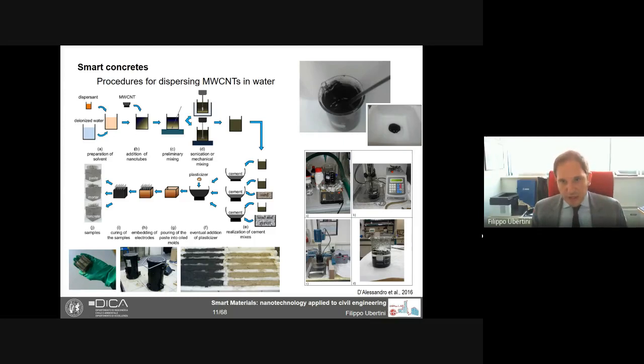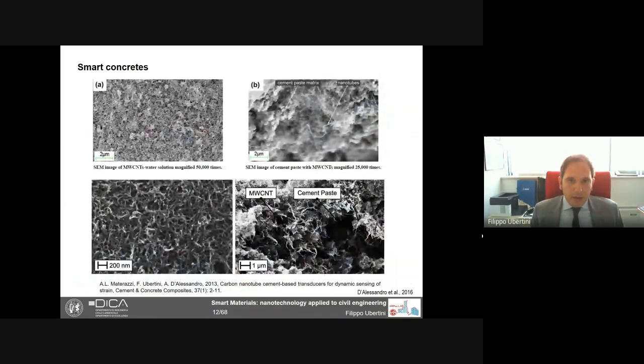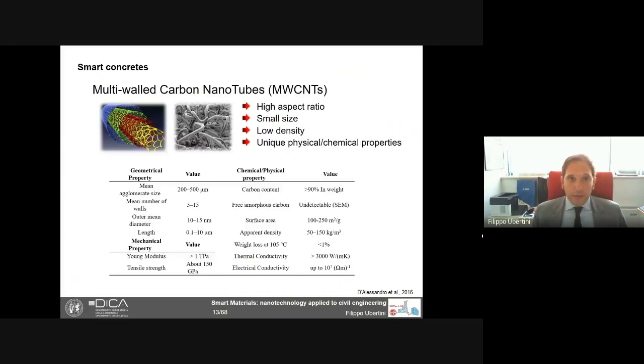Here you see some sketches, some figures from our lab, and note the difference in color between a plain cement paste and a cement paste that has just 1% of multi-wall carbon nanotubes with respect to the weight of cement. The change in color is quite strong. Here you see some scanning electron microscopy images of nanotubes after dispersion in water, after water evaporation, as well as in the hardened cement matrix, where you see that the nanotubes form this sort of very nice spider network that creates the conductive paths through the material.